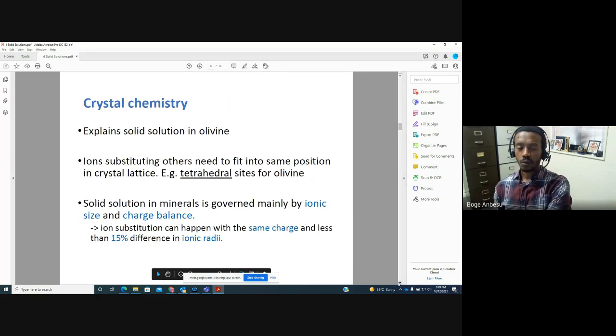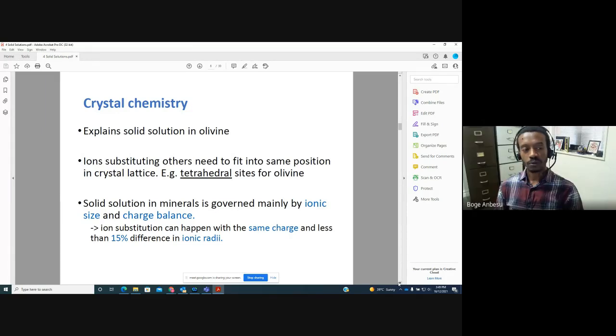So why is it occurring, or why do we see this in nature? It comes down to the crystallography of olivine and one magnesium atom being replaced by an iron atom, and so on. So for solid solutions to occur naturally, there are two basic requirements. You can have more, but the main requirements are that one, the ionic size of one should be comparable to the ionic size of the other one. So in this case, the magnesium size should be comparable in size to the iron. If one is too big and the other one is not comparable in size, then they don't actually replace one another in the lattice. Okay.